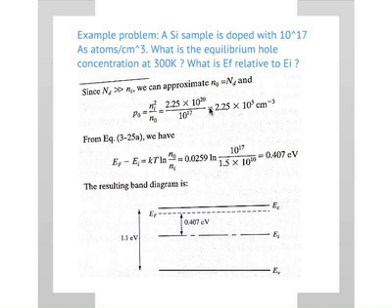Okay, so now, of course, to calculate where the Fermi level is. We know this is N-type, so the Fermi level is going to be closer to the conduction band. We know that. That's simple. From the equation before, EF minus Ei is kT ln(n0/ni), and I just plug in the numbers, put everything in, and you get 0.4 eV. So that's how you do the calculation.